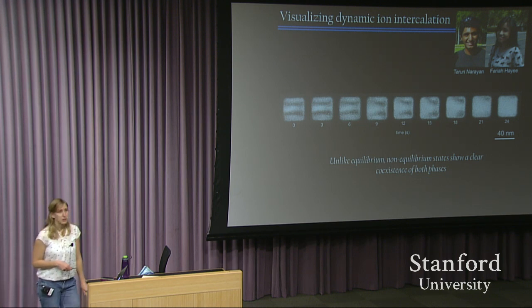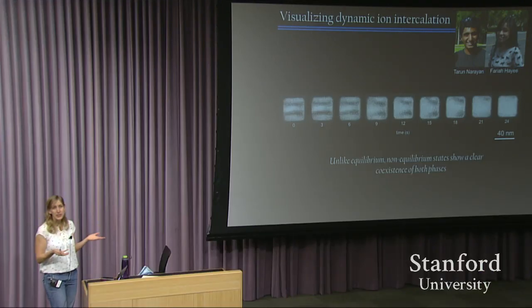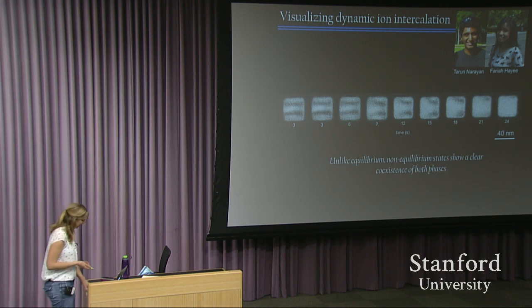So when we first captured this movie, we're like, oh, this is really cool. It shows that unlike those equilibrium measurements that I just presented, these non-equilibrium states show a clear coexistence of both phases. So in equilibrium, if we have a single crystalline nanoparticle, we don't have phase coexistence. But in order to get from one phase to another phase, we do need to have coexistence. And it turns out that coexistence is actually within the bulk of the nanoparticle.